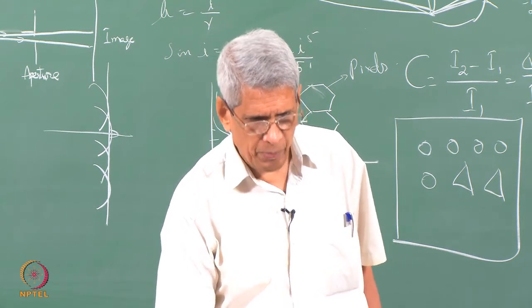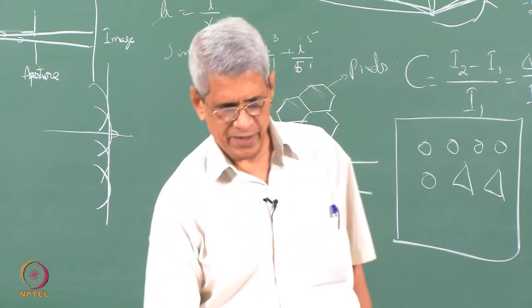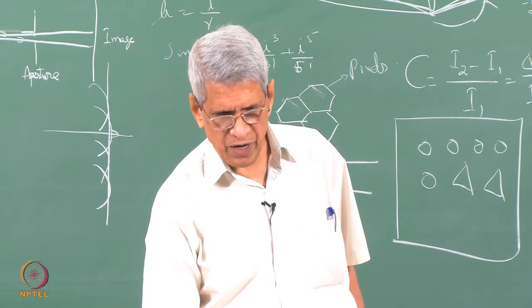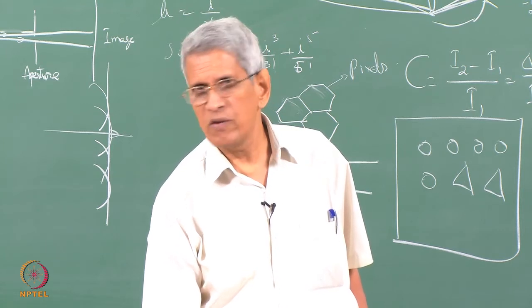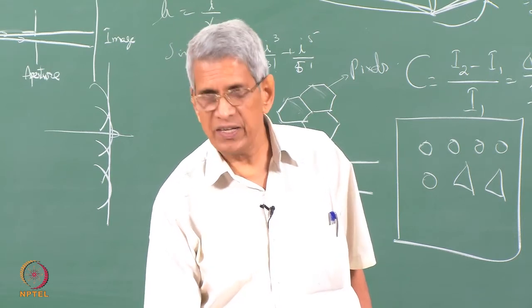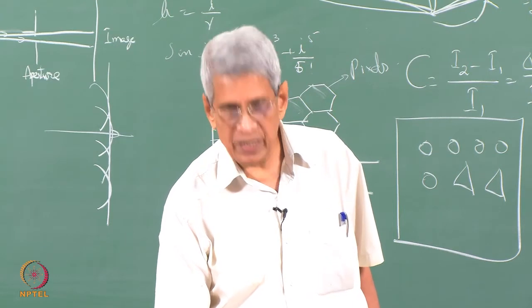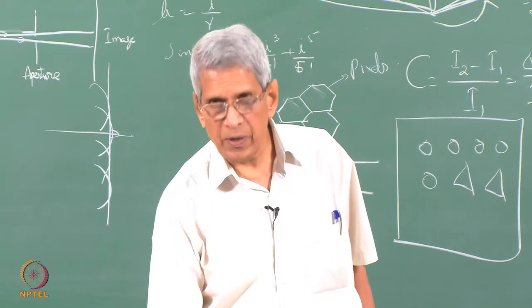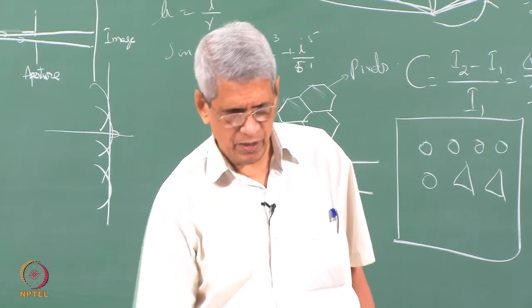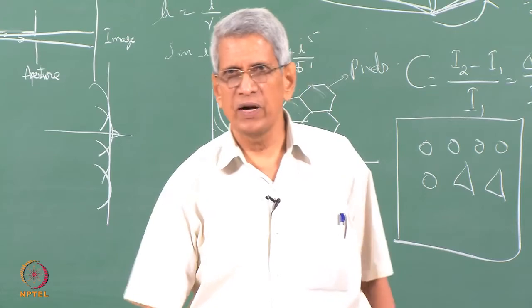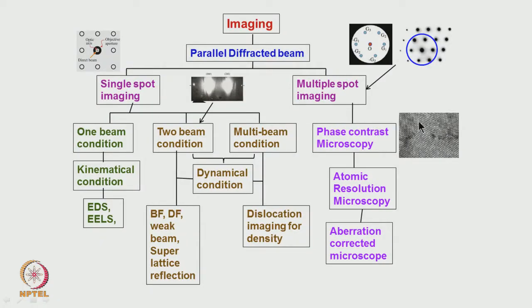Even with the parallel beam, suppose we put an aperture around all the spots and then try to form an image. Then from different regions, when the beams come and join together, a phase difference is created, and this phase difference will come as an interference contrast. This is called phase contrast microscopy, and when multiple beams are used, we get a dot image pattern. This is called high resolution microscopy. All these aspects will be covered separately in different classes in detail.